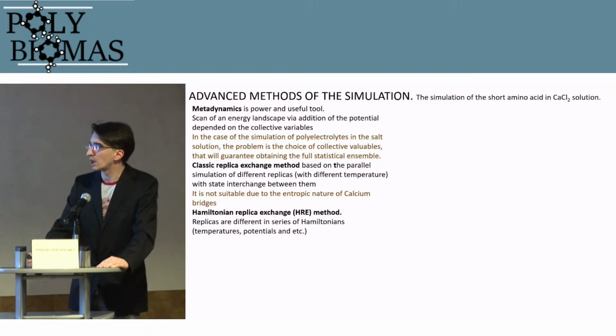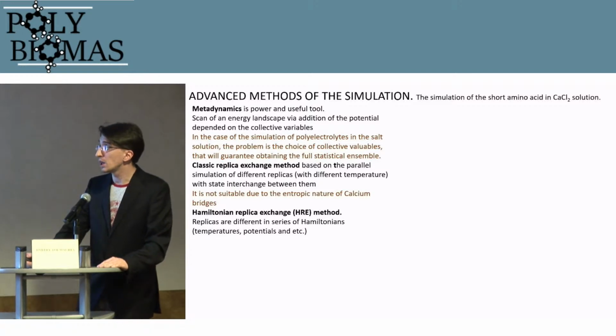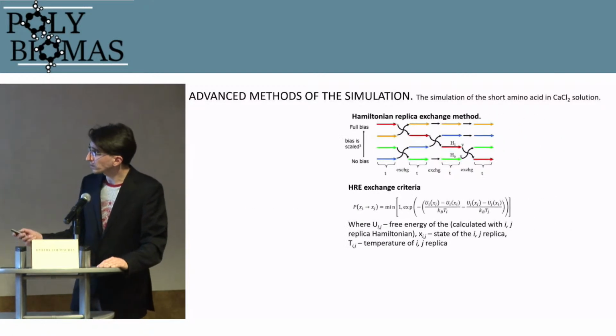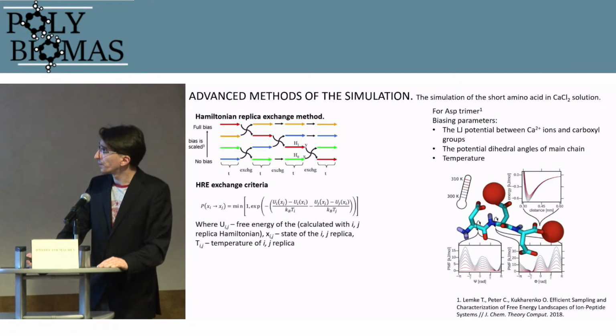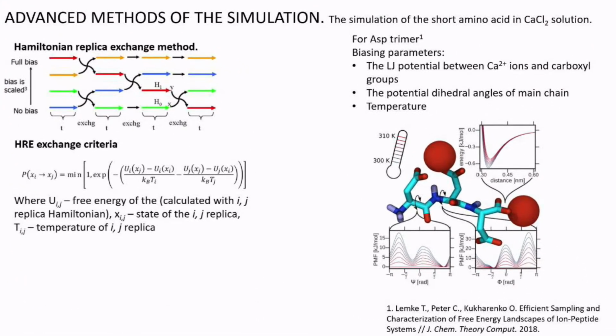The last method that we used here is Hamiltonian replica exchange. The same, we model in parallel several replicas, which differ in a series of Hamiltonians, and in our case there was the work of Lemke et al., who suggested using three Hamiltonians. The first is the Lennard-Jones potential between calcium and carboxyl groups. In higher replicas, we artificially increase the distance between calcium and carboxyl groups. Then in higher replicas, we change the potential of the dihedral angle, making it more flexible.